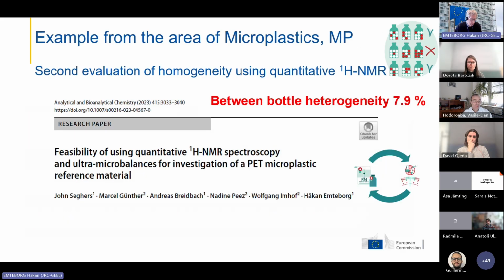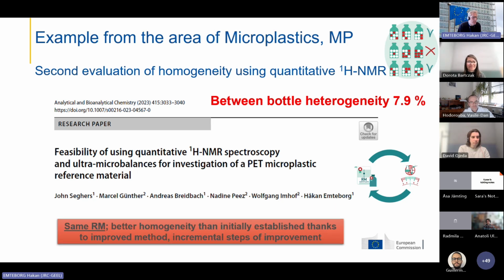Later on, we devised a QNMR method where, with a better method, we could actually prove that the same material had an even lower between-bottle heterogeneity than we actually envisaged or understood from the beginning, just because we had access to a better method. And nowadays we have access to an even better method, but I will not go ahead of that. We want to publish that before I show those results here. So indeed, it's the same reference material, the same salt cake, but with better homogeneity than initially established thanks to an improved method, incremental steps of improvement, and this is what it's all about.